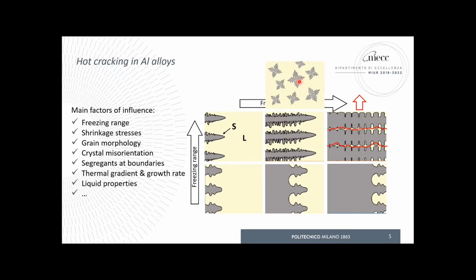Among the main factors, of course, there is the freezing range. We mentioned it. The extent of the shrinkage stresses, the grain morphology, equiaxial versus columnar, and many others. More in detail, crystal misorientation also plays a role. The larger the crystal misorientation, the higher the probability of having cracks. Segregation at the boundaries, of course. The liquid pockets are also stimulated by low melting point constituents. Of course, the environment around this liquid, the thermal gradient, the growth rate, and everything that goes with them. The liquid properties in terms of capillarity, surface tension, and many other things. So it's a very complex scenario.